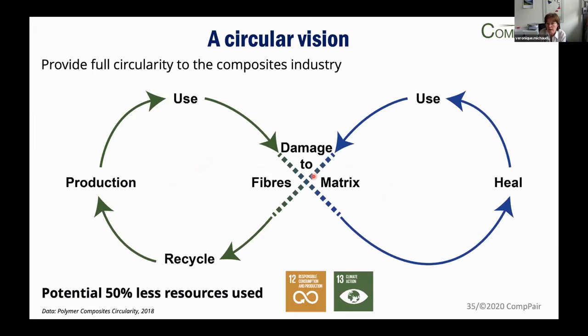The idea being that if you have damage to the matrix in your part, then you can just heal and use it again, and then maybe you will have a damage again, but you can heal and use. So you can follow this route. Now, of course, if suddenly you have a damage that is going to the fibers and we cannot really repair or not repair enough, then we have a route to recycle the material. And it turns out that with our special matrix, we are working on this right now in the project, we have a somewhat better recyclability than with the current normal epoxy composites.